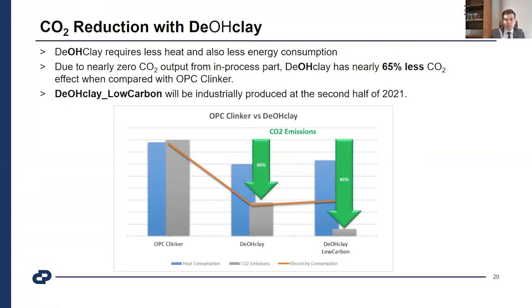When we look at the CO2 emissions part, there's a drastic drop with DeOHclay. Per ton of DeOHclay, emissions are 65% less than producing 1 ton of OPC clinker. And with the adaptation of secondary fuels, the only source of CO2 while producing DOH clays comes from the combustion part, not the in-process raw material part, because there is no calcination or decarbonation.